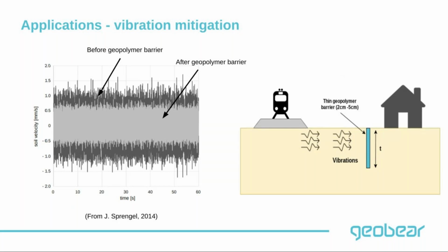And actually, some work and testing has been done in Germany that shows the effect of having these very thin sheets and their effects on vibrations. And it was concluded that with these sheets, you can reduce ground-borne vibrations by up to 60%. Now, the depth of that sheet is really dependent on the type of vibrations that we're getting and the frequencies, but it all can be designed for and mitigated.